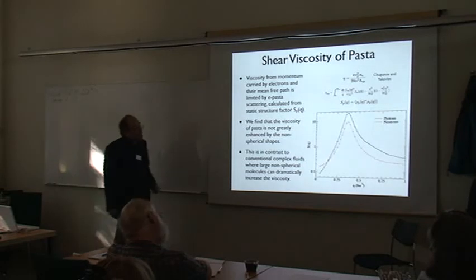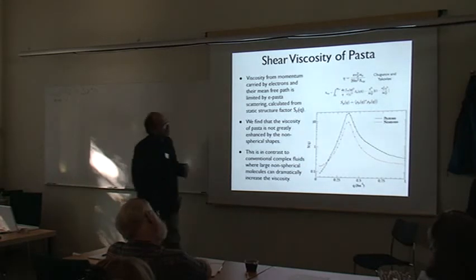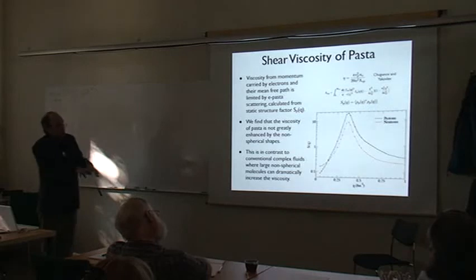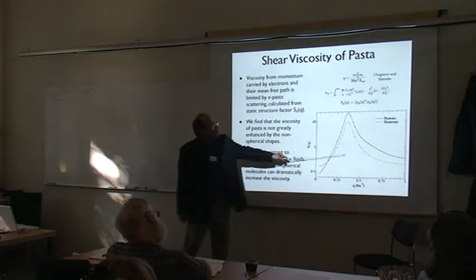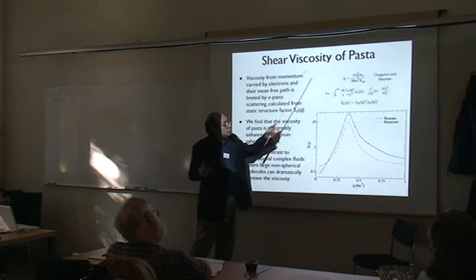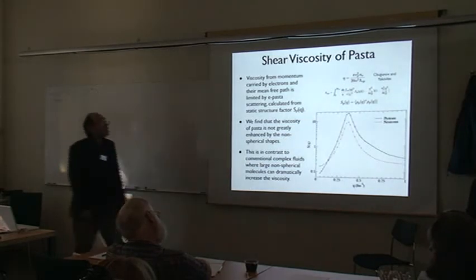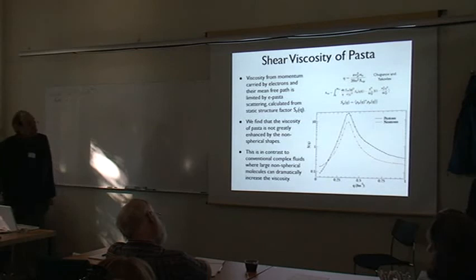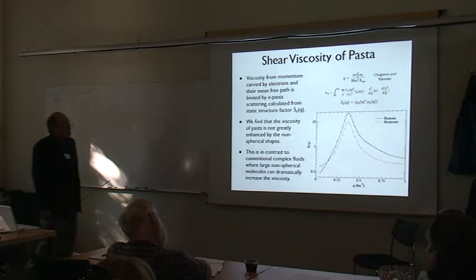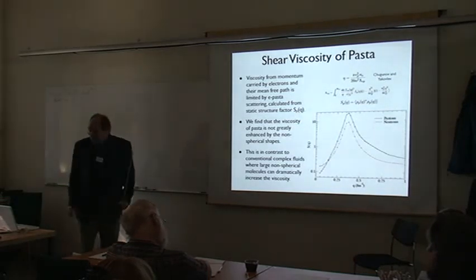Nevertheless, the finite size and the ion screening—because the pieces of pasta are packed in really close together—mean this effective number of protons only rises to about 20 or so. You can never get a situation, at least in our simulations, where you're scattering from thousands of protons.